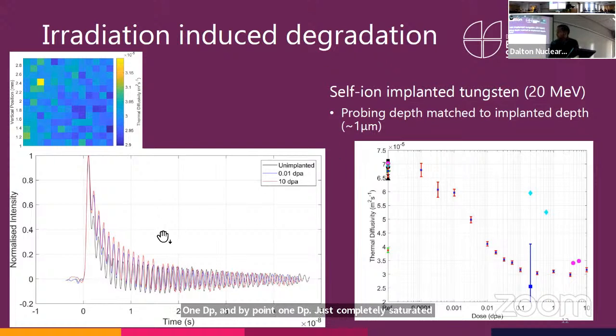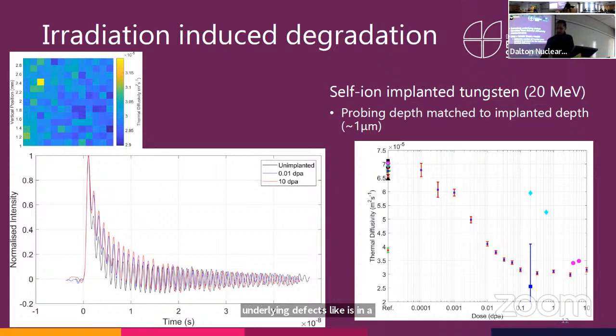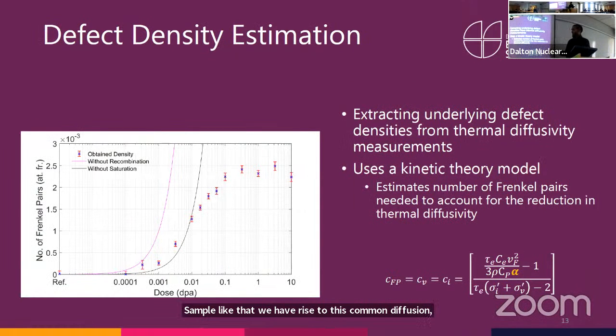And here, just to show how the method works, I have a sample that's 10 dPa, 0.01 dPa, and unimplanted, and you can see the rate of decay increases as you decrease the dose, and vice versa. And since we got really good error bars with this because of the temporal and spatial averaging, we decided to go and try to extract what the underlying defects are in our sample that gave rise to this thermal diffusion degradation. Then we used a simple kinetic theory model that gave you your Frenkel pair density from your thermal diffusivity, basically estimating how many Frenkel pairs you needed in the sample to give this degradation.